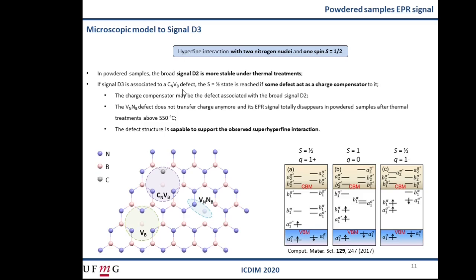A possible candidate that meets these conditions is the boron vacancy complex with a carbon impurity on the nitrogen site, this defect here, CNVB. By DFT calculations, it is predicted that this defect reaches a paramagnetic state with spin one-half when an electron is donated or accepted by the defect. Since the carbon isotope without nuclear spin is dominant, the nitrogen nuclei in the first vicinity of the boron vacancy, here nitrogen and this nitrogen nuclei, will give rise to the super hyperfine interaction necessary to generate the 5 lines observed in the EPR spectra.